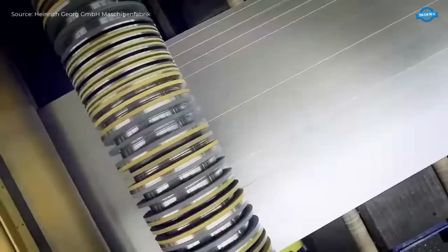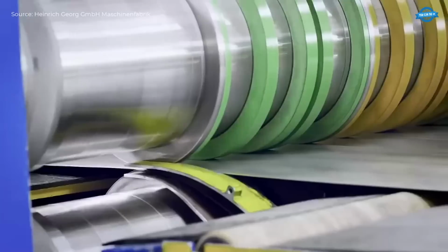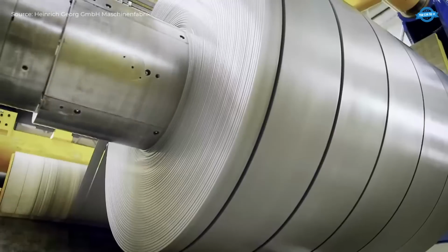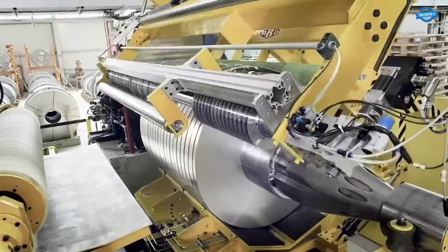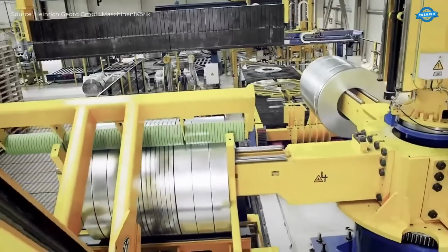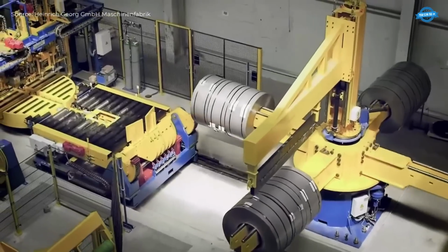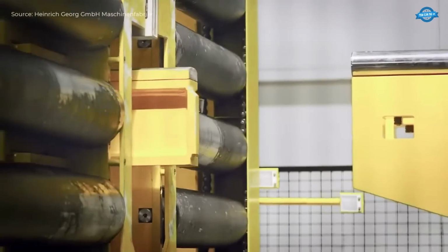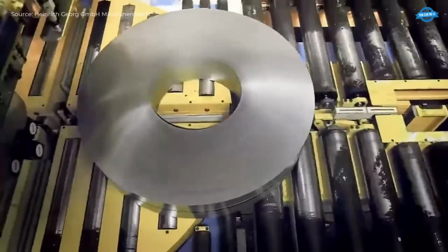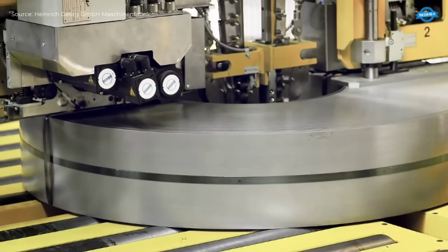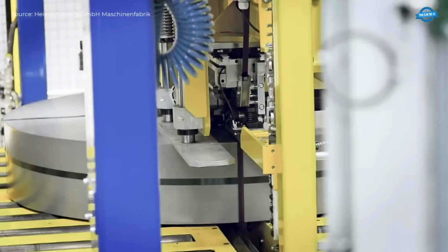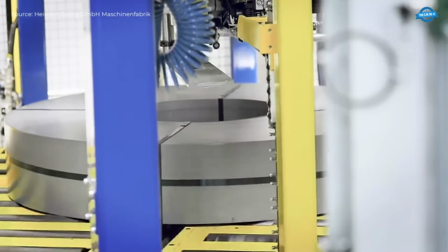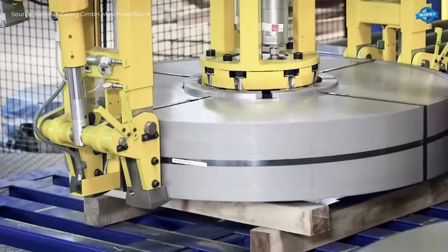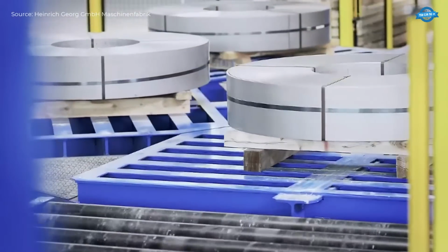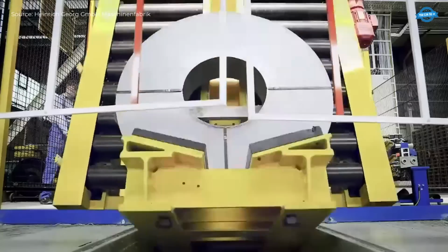This slitting line also offers exceptionally gentle handling of sensitive materials, such as automotive surfaces, coated strips, or annealed stainless steel, through surface-adapted braking techniques. It features energy-efficient regenerative systems and specially rated drives to minimize power consumption. Built for strength and durability, the line processes materials with tensile strengths exceeding 1,400 N per square millimeter and yield points up to 1,000 N per square millimeter, making it ideal for demanding industrial applications.